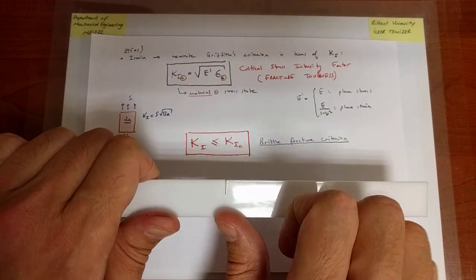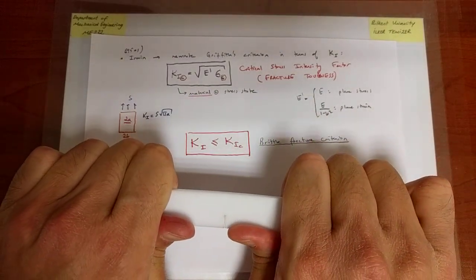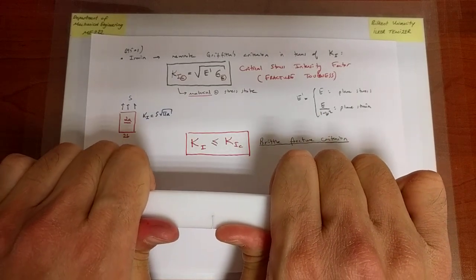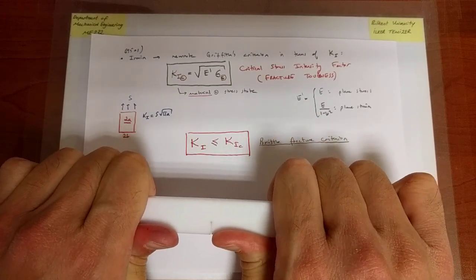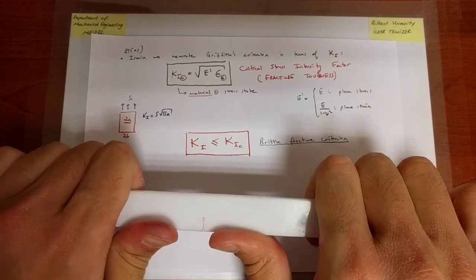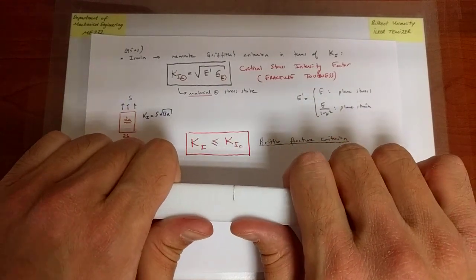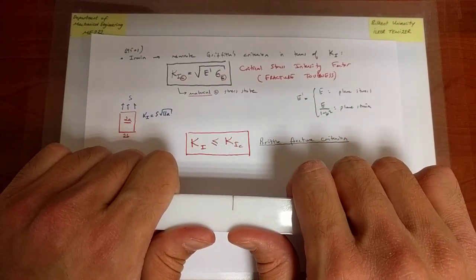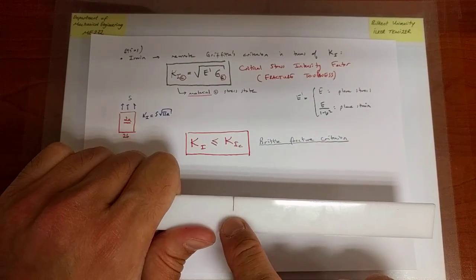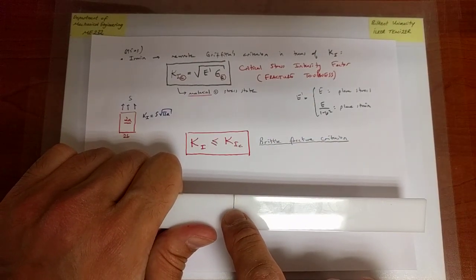and I'm going to try to again bend it in this fashion. Here I applied a huge amount of force. You can perhaps even see the specimen bending a little bit and nothing happens. But in this case, I'm going to load the structure, and there is a crack. At the tip of the crack there are huge stresses.